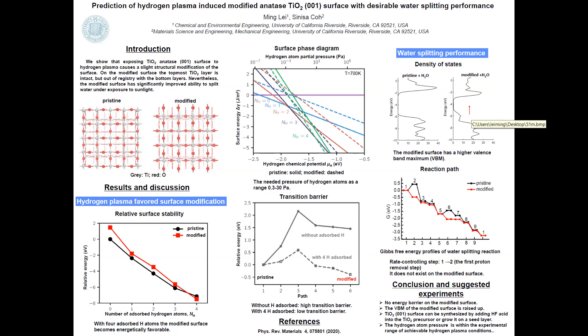To test this hypothesis, we study the water splitting reaction path on the surface. The last figure shows the free energy profile of the two surfaces for the water splitting reaction. For the black line, it shows the case for the pristine surface. We find the rate-controlling step on the pristine surface is from step one to step two, which is the first proton removal step. However, this rate-controlling step does not exist on the modified surface, which means the modified surface has much better water splitting performance than the pristine surface.